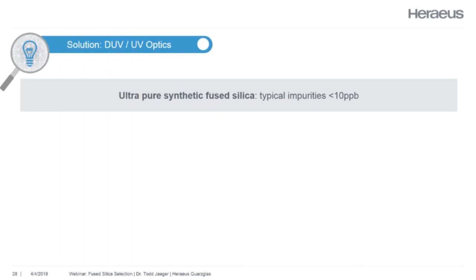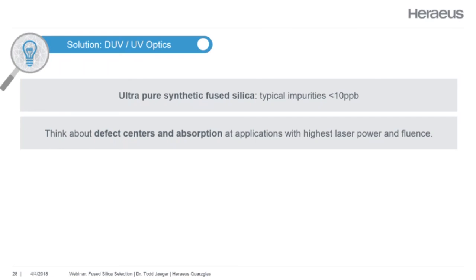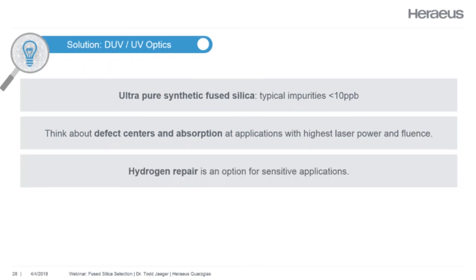You want to go for an ultra pure synthetic fused silica. The individual elemental impurities in our ultra pure synthetic fused silica are typically less than 10 parts per billion. You want to think about the defect centers and absorption at the applications. Is your laser fluence very high? In that case, you're really going to want to use a material that is not going to damage in this way. Hydrogen repair is an option.